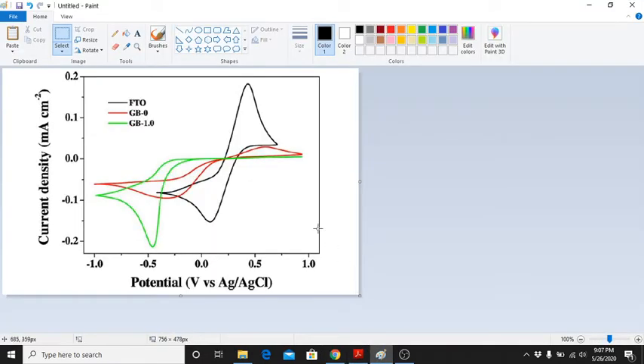This is from the other paper. Okay, this result shows what? This paper compares the bare FTO with the main material. They have two main materials where GB1.0 is the best performance. As you can see, when they immerse in the ferricyanide solution for cyclic voltammetry, the main material depicts no appearance of an anodic peak. There is no anodic peak here. As you can see, for the bare one, this part is the oxidation, we call that the anodic peak. This one is the reduction, we call that the cathodic peak. So we focus on the oxidation process. There is no anodic peak here, indicating a good blocking ability.